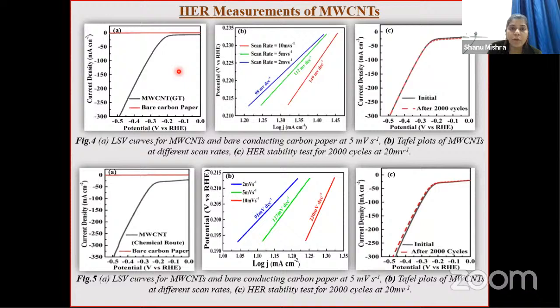So we fitted the polarization curve using the Tafel equation, which is eta equals B log J plus A. It's a well-known equation, and we plotted the Tafel slope at different scan rates for both the catalysts. We obtain a lower Tafel value of 98 millivolt per decade for the MWCNT GT and 91 millivolt per decade for MWCNT by the chemical route. This lower Tafel value is coming due to the oxygen functionality and the defects we are getting here.